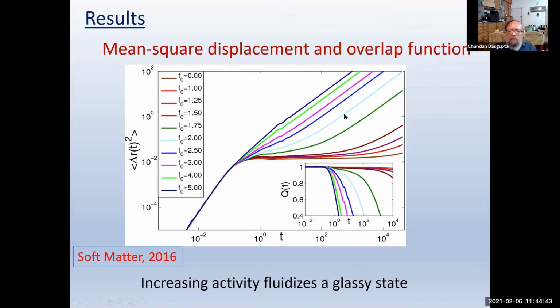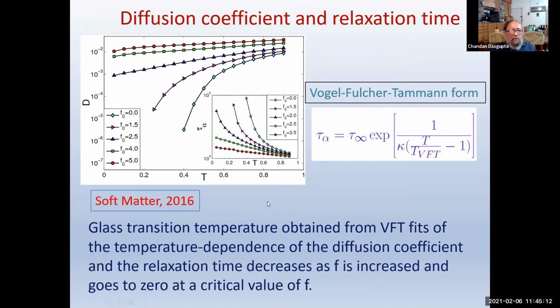One can measure various quantities. One can measure the diffusion coefficient from this, or by looking at some kind of time-dependent correlation function, one can measure the relaxation time. And as you can see here, the passive system doesn't relax at all. This correlation function basically remains fixed at 1, but then it begins to decay as one increases the activity, and then one can see how the relaxation time is changing as a function of activity. So this is shown here. This shows the diffusion constant as a function of temperature. This shows the relaxation time as a function of temperature for different levels of activity. For zero activity, it is this curve or that curve.